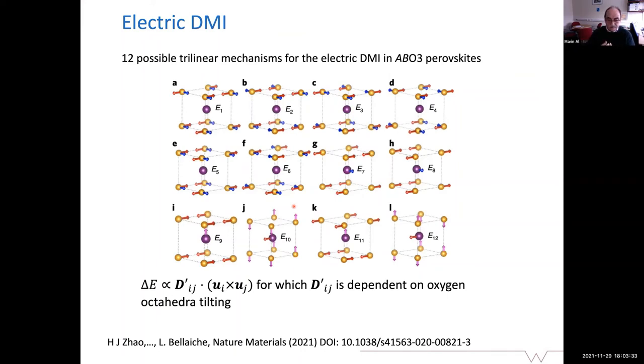Nevertheless, it was a great help for us to read a paper from Bellaiche's group, published almost at the same time, which described a possible trilinear mechanism for an electrical equivalent of Dzyaloshinskii Moriya interaction. In this case, the Dzyaloshinskii Moriya vector comes with the oxygen octahedra tilting, which will tilt the polarization. And there are a number of them. You see, there are 12 possibilities.